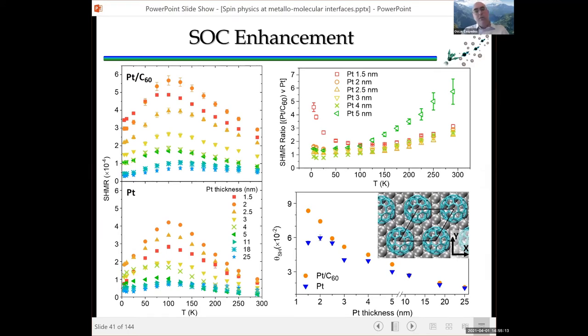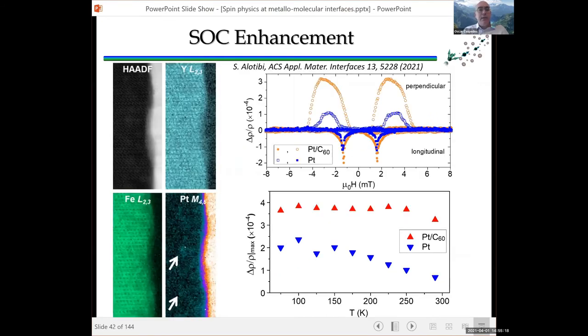This effect can also be seen in AMR measurements of the platinum. As you can see, adding C60 to the platinum GIG structure doesn't change the shape of the AMR, but it does increase the effect of the AMR by a factor 2 to 3 or 4. And it also makes this AMR more stable at higher temperature. So in platinum C60, you can easily see that AMR at room temperature, and it has a very similar magnitude to low temperatures. Whereas without the C60, that AMR really is starting to die off at high temperatures.